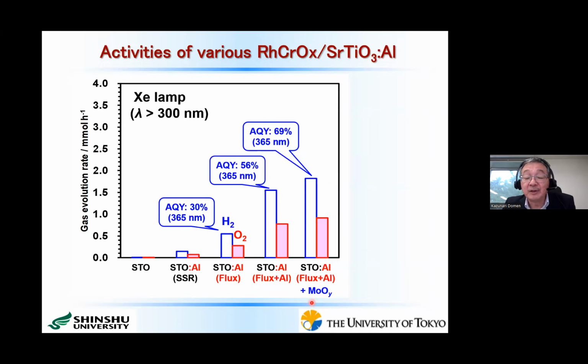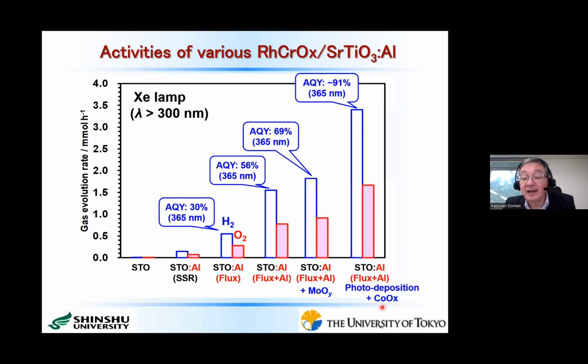However, more recently, we realized that when we switch this molybdenum oxide to cobalt oxide, more precisely cobalt oxyhydroxide, and all the metallic components of the co-catalyst, I mean the cobalt and rhodium and chromium, were photodeposited, the apparent quantum yield exceeded 90%. This is extremely high quantum efficiency for overall water splitting reaction.